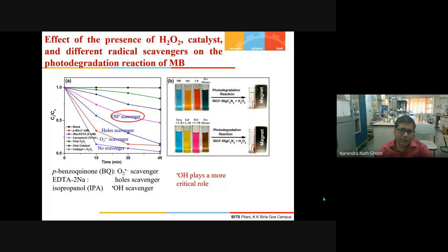We did a very simple experiment. First, let me explain this graph A. The black line, which you see, is where we took no catalyst, just the dye solution. We have shown that up to 45 minutes, which is the time period of our study, without catalyst and without hydrogen peroxide, almost no decomposition is happening. Though there is a high possibility that due to a long exposure to sunlight the dye itself can decompose, within this time frame we have not seen any noticeable decomposition.